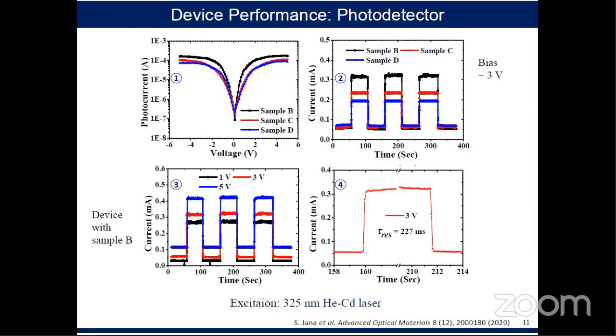From figure 3, we have used bias dependent temporal modulation. As the bias increases, the generation of photo electrons and holes increases, so it increases the photocurrent in our external circuit. The response time is presented in figure 4, where we have found that the response time of the device with sample B is almost around 227 milliseconds. All the excitation used was a 325 nanometer helium cadmium UV laser. So next slide.